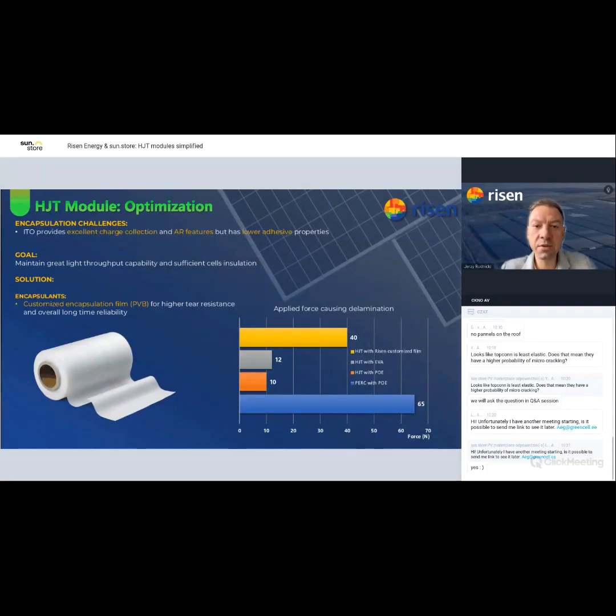And the last thing when it comes to this part, namely the encapsulant. This front layer of the HJT cell, ITO, provides, as I said, excellent charge collection and also very, very good anti-reflection features, but it has lower adhesive properties than the anti-reflective coating of other technologies such as PERC and TOPCon. And so if we used EVA or POE, we would have a problem, because the applied force that causes the delamination would be significantly reduced. So this would affect in the end the reliability of the product.